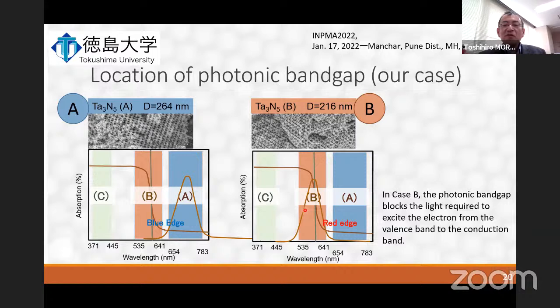The photonic band gap blocks most of the light required to excite an electron from the valence band to the conduction band. While in sample A, the reflected photons in the blue region, whose wavelength is longer than the absorption edge, cannot activate tantalum nitride to generate carriers. Namely, photons with high energy can be fully absorbed by the tantalum nitride photonic crystal. As a result, sample A with blue edge slow photon effect gave higher hydrogen production than sample B with red edge slow photon effect. Okay.